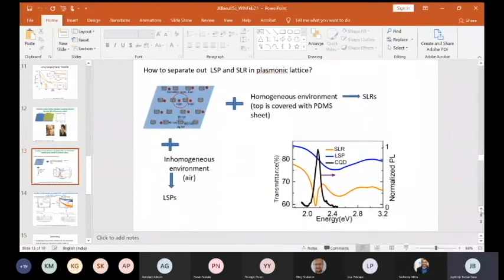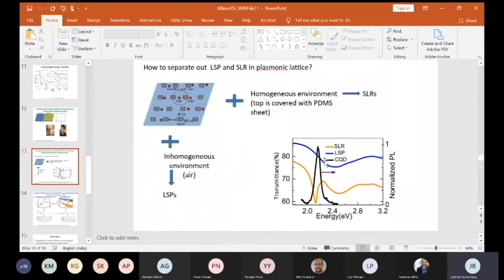observe is very interesting. So first of all, in this case, the emission spectrum is clean, as you would expect for an uncoupled quantum dot. There is no coupling because the coupling strength is very weak, and the concentration is very, very low, much lower than what I discussed in the previous two pieces of work. So essentially, that is out of the picture. So spectrally, you basically do not see any signature of any coupling, right?